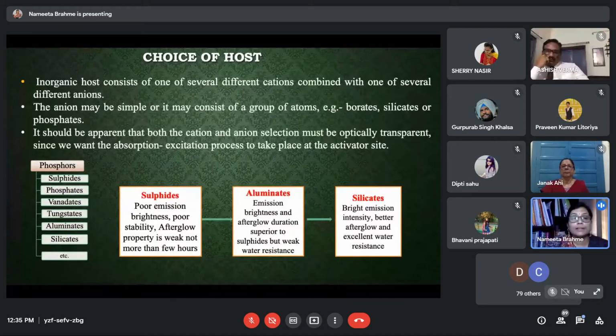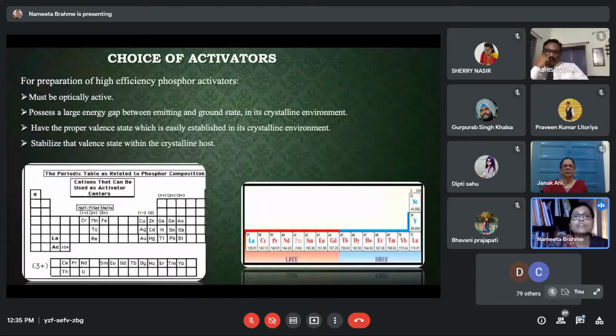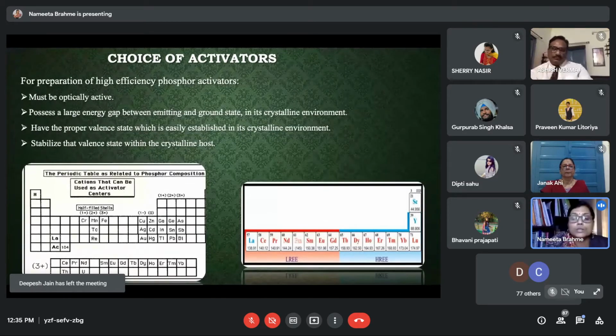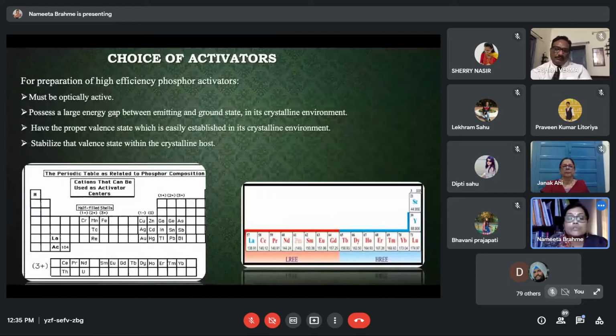Now the second thing, very important for the preparation of a high efficiency phosphor, is the choice of activators. Here, the factor to be considered is the so-called ground state perturbation. As we know, the activator site is under the influence of vibronic coupling involving localized phonon modes. This includes both phonon creation and destruction, and also the time varying electric field of the lattice, which produces vibrational perturbation at the activator site. So we have to minimize that vibronic coupling effect by proper choice of the activator.